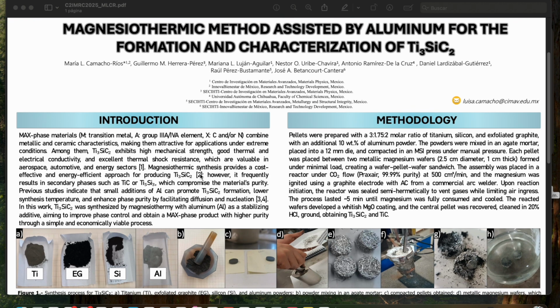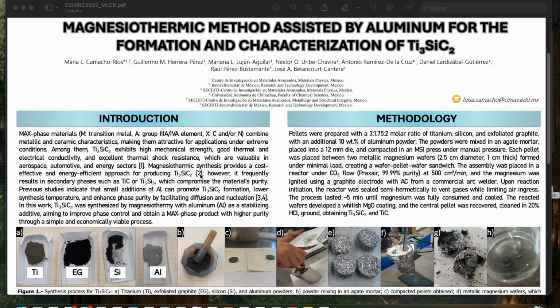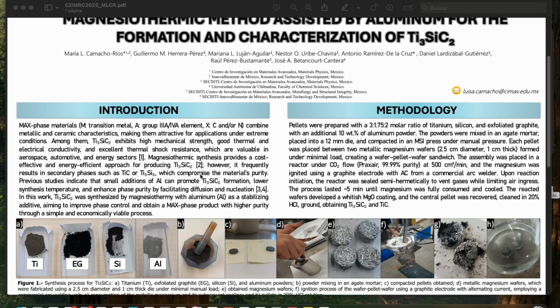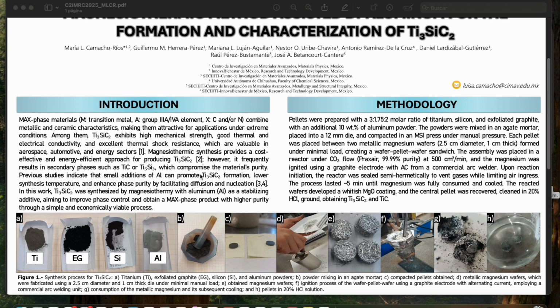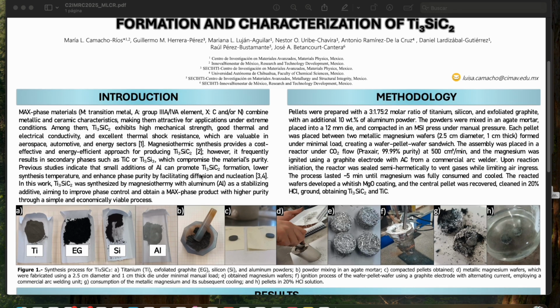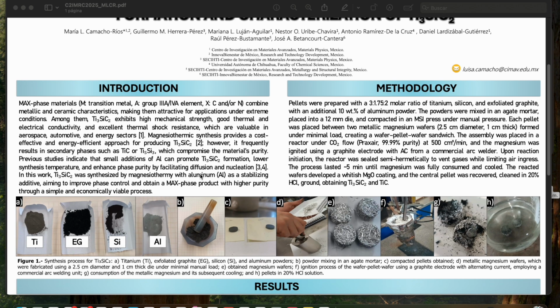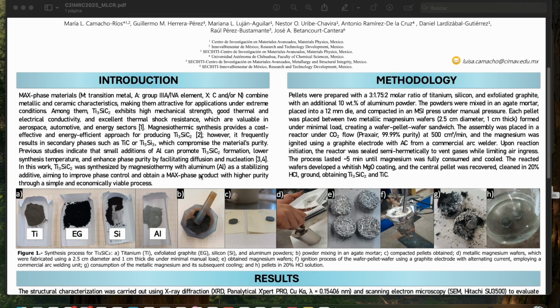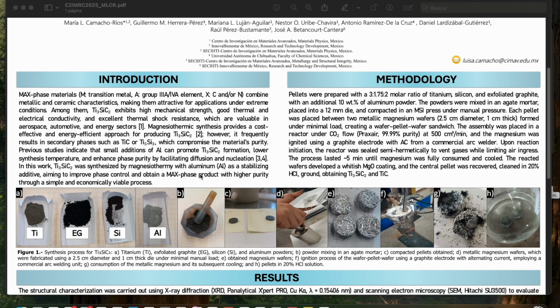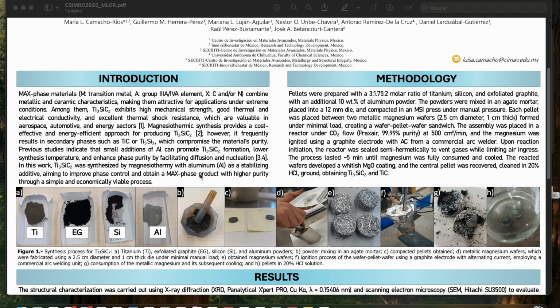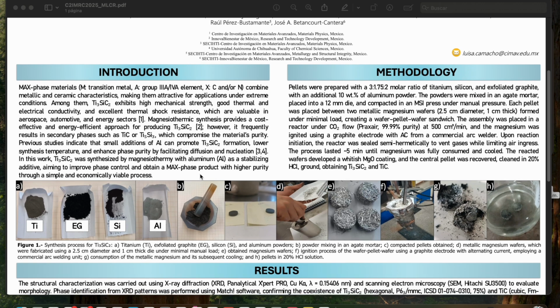The processing concept is a wafer-pellet-wafer sandwich that couples intimate contact with a controlled exotherm. Powders of Ti, Si, and exfoliated graphite were mixed at a 3:1.75:2 molar ratio with 10 wt% Al, pressed into 12 millimeter pellets, and clamped between two magnesium wafers of 2.5 centimeters diameter and 1 centimeter thickness. The assembly sat in flowing CO2 at 500 cubic centimeters per minute.